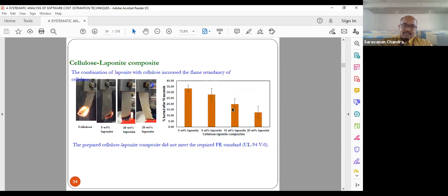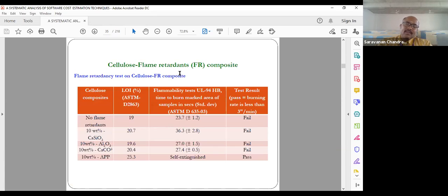This is the flame retardancy when we add cellulose with Laponite clay. As you can see here, only cellulose is burning more. When you add 10 and 20%, at 20% it is not burning. However, it does not meet the international standard. We varied the different fillers and flame retardants, from calcium silicate to aluminum oxide and calcium carbonate. All of these failed to meet the international standard.